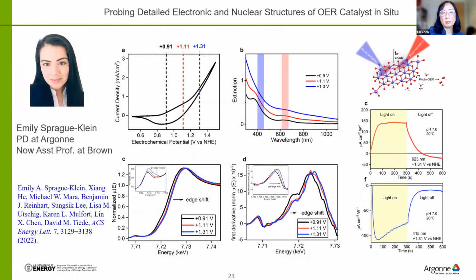chemically generated cobalt-4. Then Emily Sprague-Klein continued, mostly focusing on this Co-Pi, which is an extended structure that Dave Tiede and his postdoc also studied with PDF. The main discovery she observed using X-ray spectroscopy is that if you excite in the blue light region, it creates an LMCT transition, so that the metal is reduced. But if you excite in the red region, it is going to be oxidized. Previously, we always thought this was an electrochemical electrocatalyst, so the photoactivity had not been examined.